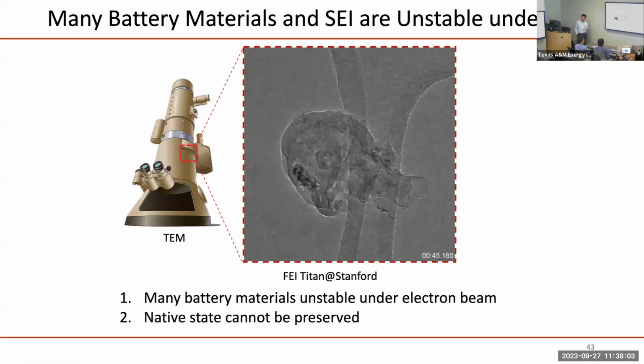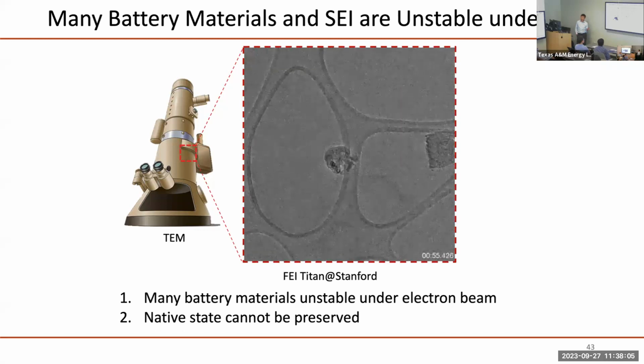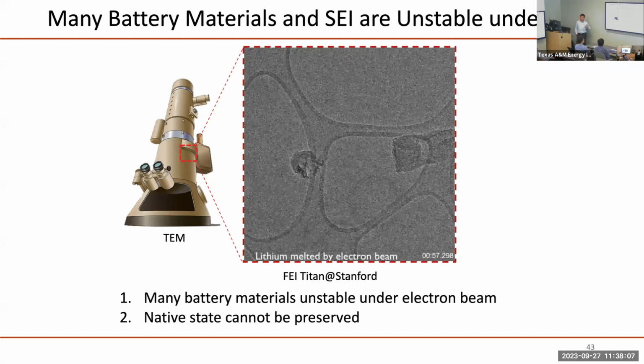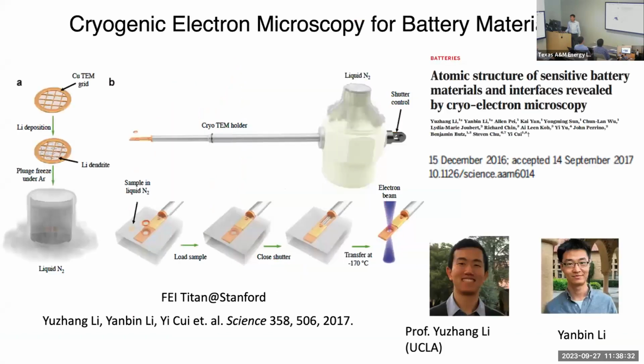Metallic lithium's melting point is roughly 180 degrees Celsius. Its melting point is very low, and the bonding is very weak. You're going to destroy this structure. Nobody sees atoms of lithium. Even though the lithium-ion battery has been used commercially for 30 years, since research in 1970 until now, close to 50 years, nobody sees atomic scale resolution of metallic lithium. And to understand the interface is not possible.